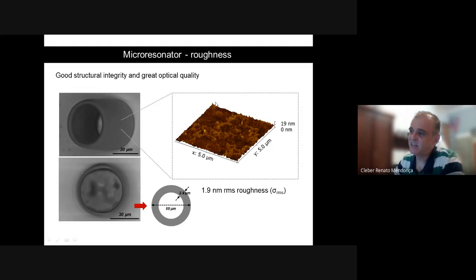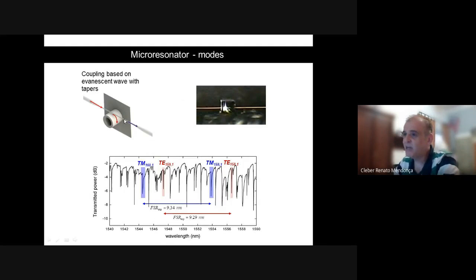Here is an atomic force microscopy of our resonator. As you can see, the average roughness is on the order of 1.9 nanometers. So it's very good. It's a very nice resonator that we are able to fabricate. And then we couple light to the resonator. How do we couple light into the resonator?